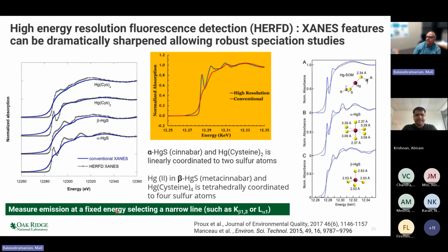By measuring X-rays at a very fixed energy, you can overcome to some extent the core hole lifetime broadening. So here is a mercury L3 edge, and you can see that this red line here is what you measure with conventional XANES. But if you monitor emission by looking at this L alpha emission in this case, you will sharpen the features. And this is called high resolution fluorescence detection. And this is very powerful because once you increase the resolution beyond what is intrinsic core hole, you might start seeing features which can help you speciate different samples.